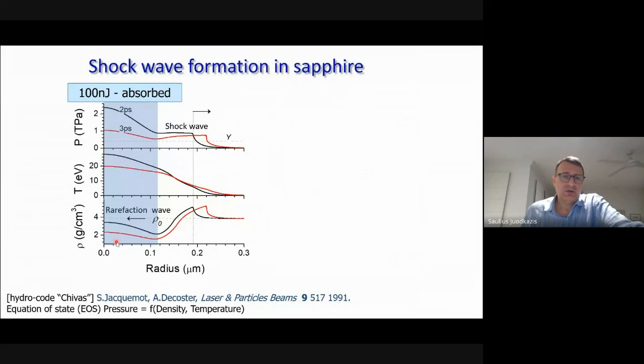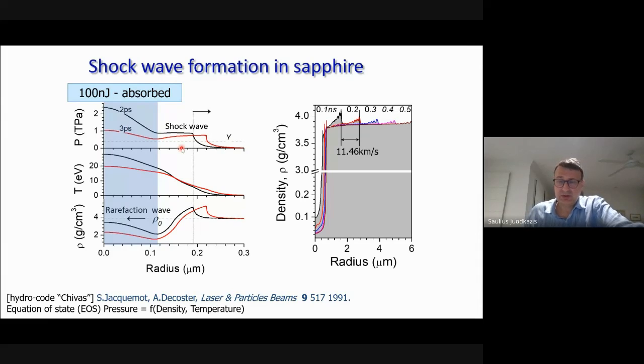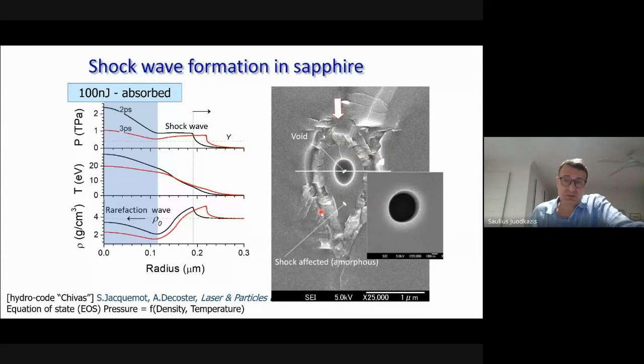Modeling was carried out for the conditions of energy delivery, calculated as spherical. So this is a radius with deposited energy. And then what happens with the pressure, temperature, and density in the first picoseconds is shown here. We have a shock wave, which is pushing material. Young modulus, this is that dashed line. So the shock wave is actually exceeding strongly the Young modulus. No surprise that we have modification of material, of sapphire. On the longer time scales, we still see shocks propagating at velocities which are larger than sound velocity in sapphire, and we see the opening of the hole. So this is mass density. So we see the hole which is opening inside. So this really corresponds to the experiments that we see.